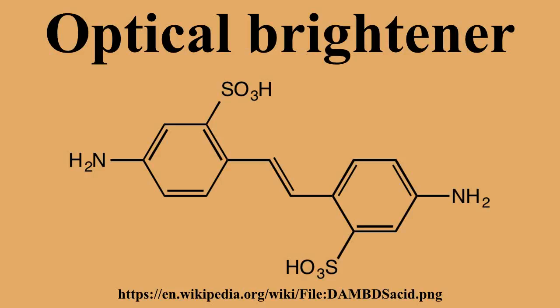All brighteners have extended conjugation and/or aromaticity, allowing for electron movement. Some non-stilbene brighteners are used in more permanent applications such as whitening synthetic fiber. Brighteners can be boosted by the addition of certain polyols, such as high molecular weight polyethylene glycol or polyvinyl alcohol, which increase the visible blue light emissions significantly. Brighteners can also be quenched; excess brightener will often cause a greening effect as emissions start to show above the blue region in the visible spectrum.